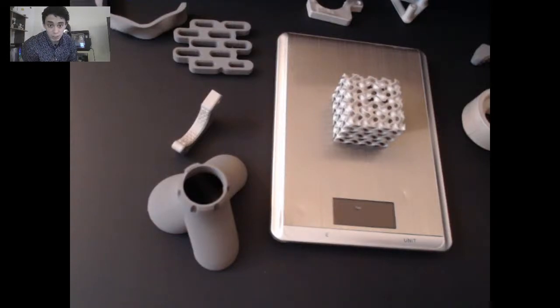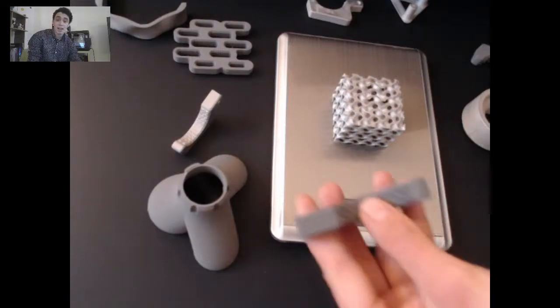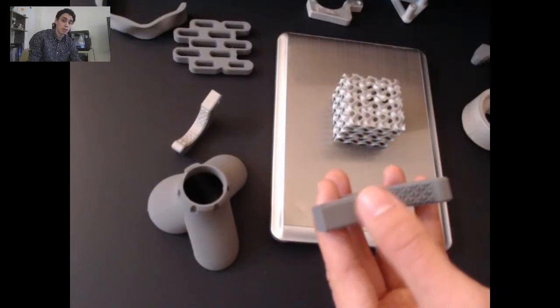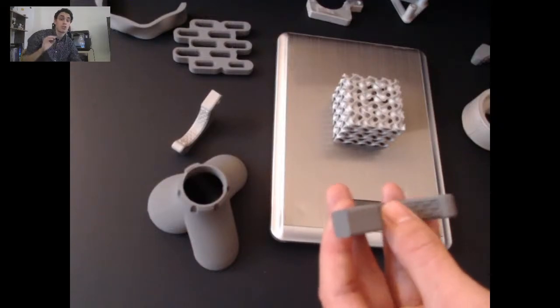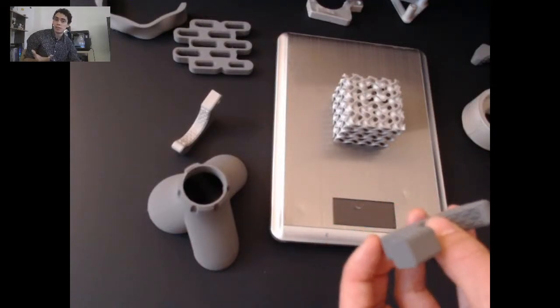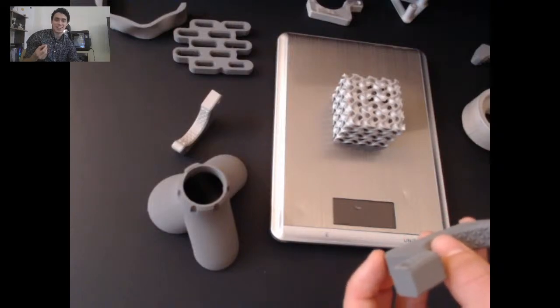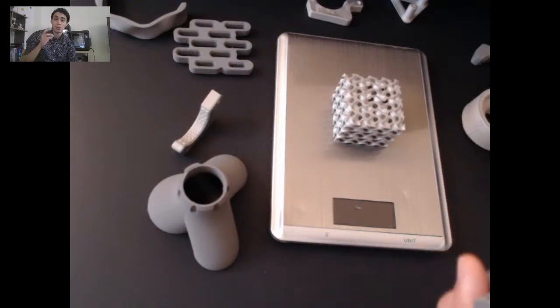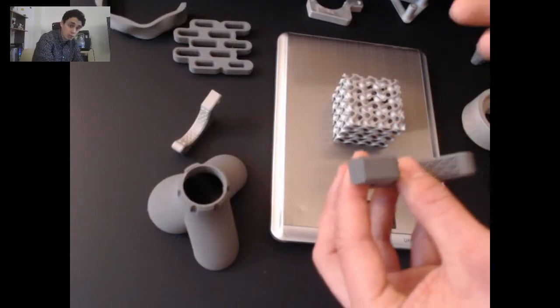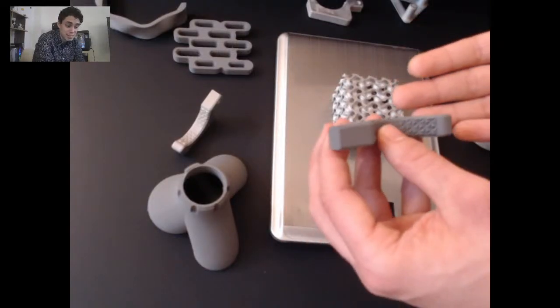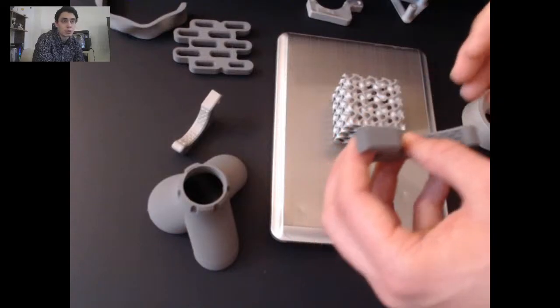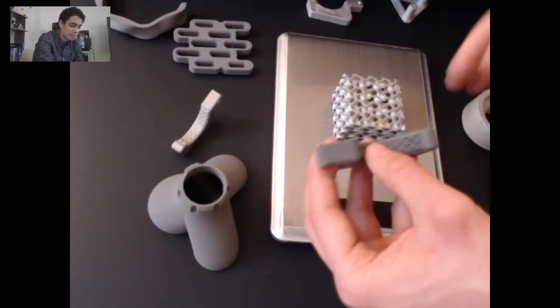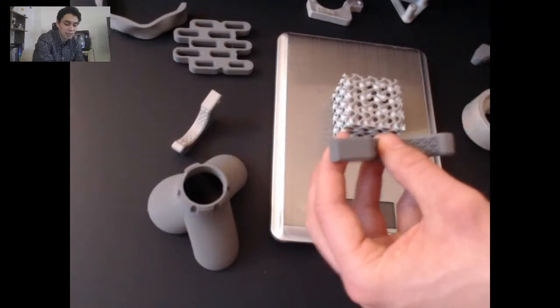Is there significant shrinking after ovening the part? If so, is it considered during the printing of the green part? That's a great question. As I said before, yes, there's significant shrinkage of the part during the sintering process. With MakerBot Print, the new slicing profile will account for some of that, but it is uneven, right? It's not super controlled. We know that it's about 20% in X, about 20% in Y, and about 26% in Z. But it's not something you will be able to 100% control, especially keeping the tolerances as tight as you would expect with the part that came out of the printer.